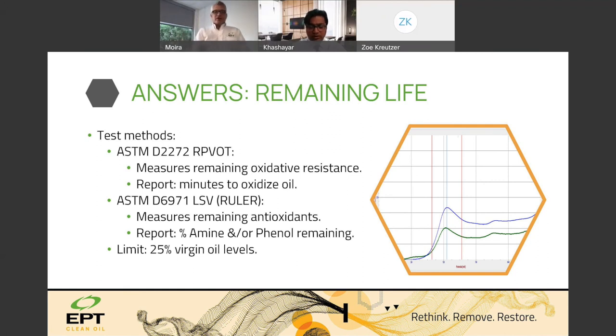Linear sweep voltammetry is a method that we can use to measure the percentage of remaining additive. Some people call this the ruler instrument. The ASTM standard is 6971, and I would recommend this test in all critical applications so that you can predict end of life in your oil years ahead of time.